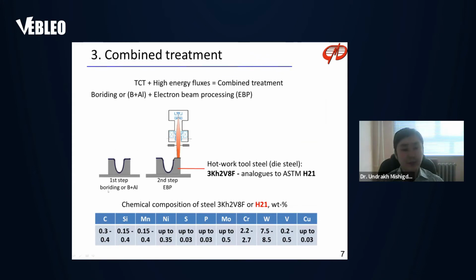As an example, boriding can be done as a first step, and the second step can be done by electron beam processing of specific places on dies. For instance, the top part and the corner are subjected to severe wear because of the high metal flow rate, and they need to be additionally modified.